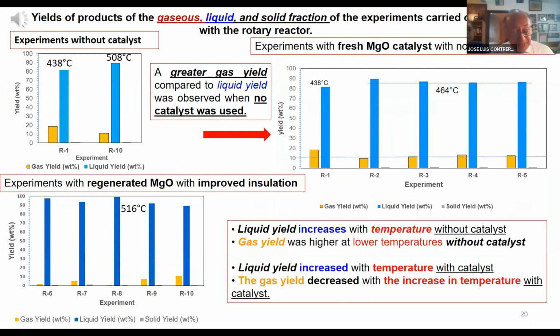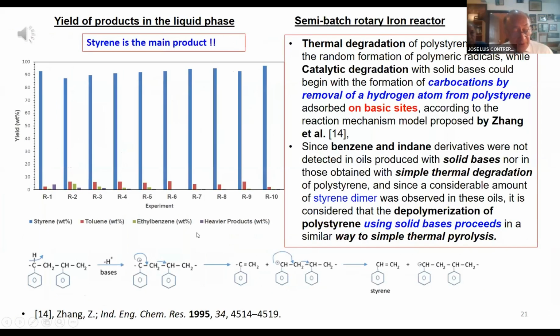A greater gas yield compared to liquid yield was observed when no catalyst was used. Liquid yield increases with temperature with or without catalyst. The gas yield decreased with an increase in temperature with catalyst. All experiments with a regenerated catalyst showed almost the same performance towards liquid product. The liquid product yields show that styrene is the main product, as you can see.